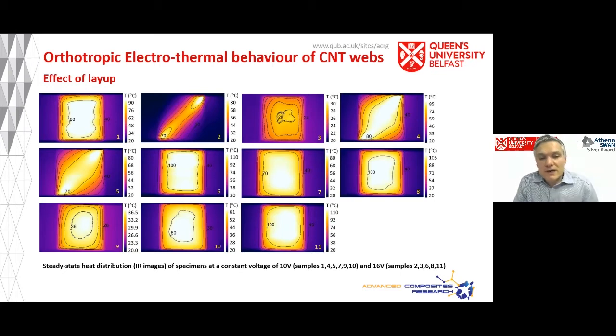Now, we've done a lot more work here also looking at the repair of these structures, and we have a protocol of how to repair these webs. Say we looked at impact damage. You don't try and repair that impact damage with a web. You can just use a mixture of carbon nanotubes and a resin. All you need to do is to recover some sort of conductivity. Okay, so that's all I'm going to say about anti-icing, de-icing, or indeed any other use that will require some sort of heating.